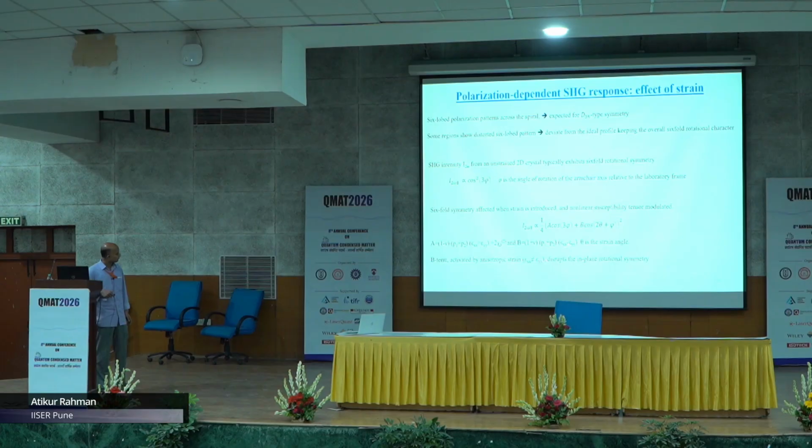But in the presence of strain or something, the intensity will change like this, where the B portion is responsible for this anisotropic strain. Now it is not symmetric, so EXX is not EYY, and that disrupts the in-plane rotational symmetry. And theta is the strain angle.